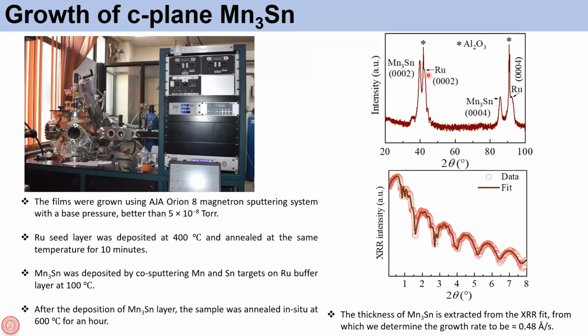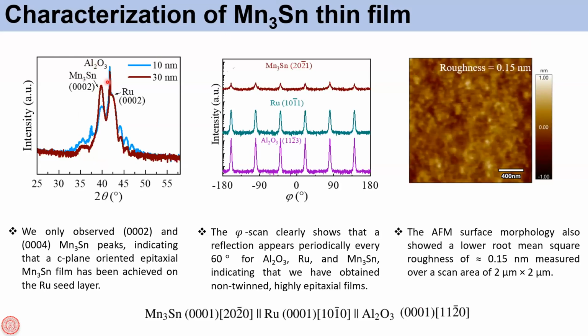We found that if you use a ruthenium seed layer and a sapphire substrate, then we can grow an epitaxial film. This growth optimization is not simple, but we finally optimized it. These are the optimized conditions after which we could get epitaxial thin films, and this shows different thicknesses for which we have nice epitaxial thin films. This phi scan confirms the epitaxial film, and this is the epitaxial relationship. The AFM measurement also shows that the surface roughness is very low and the surface is very smooth.